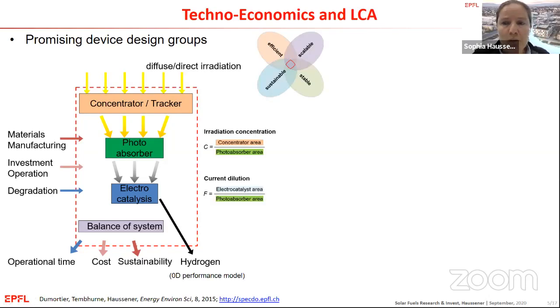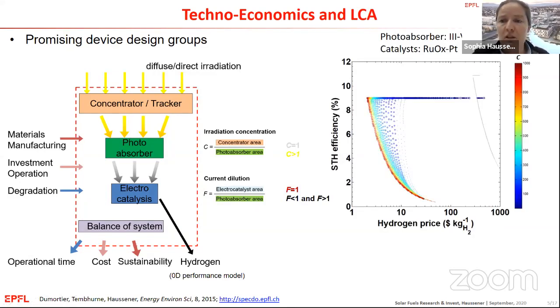And we introduced two additional performance parameters where we said, okay, if your system has a concentrator, has a photoabsorber, it has a possible co-catalyst, you can actually play around with the ratio of these materials, effectively concentrating the irradiation if you change the area of solar collection to photoabsorber area, and effectively with a current dilution if you play around with the photoabsorber area and electrocatalysis area. And so if you do these types of calculations with this C, solar irradiation concentration factor, and with this F, this current dilution factor, and you pick a certain material combination, for example, as an extreme case here, III-V based materials, you get these types of solutions.